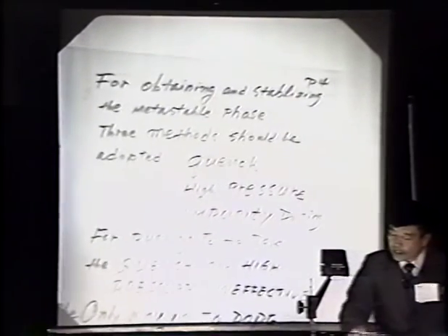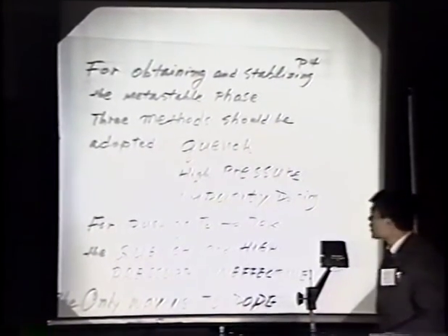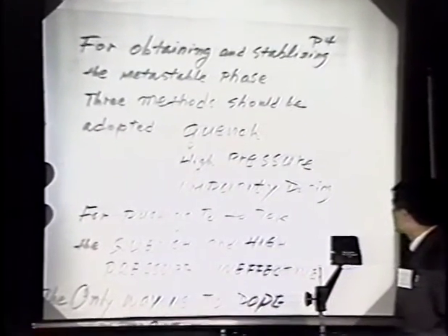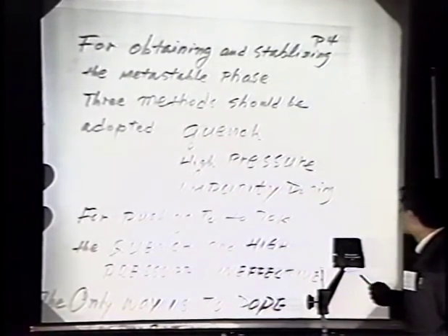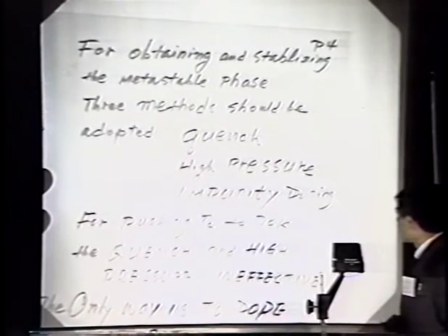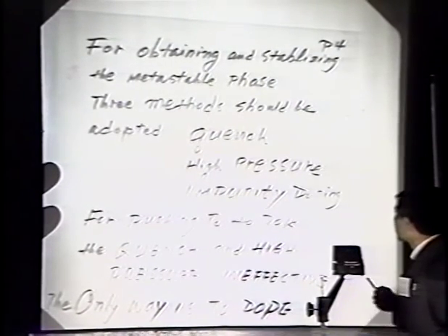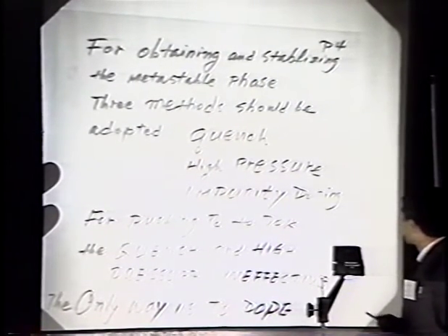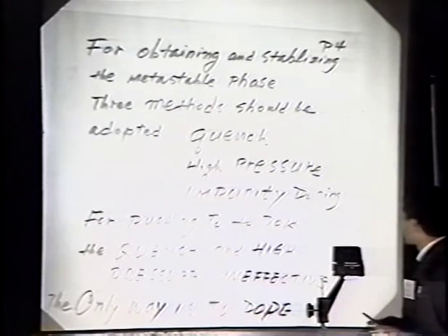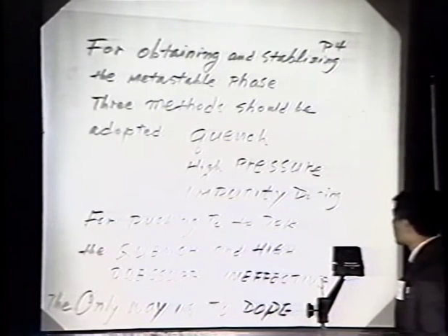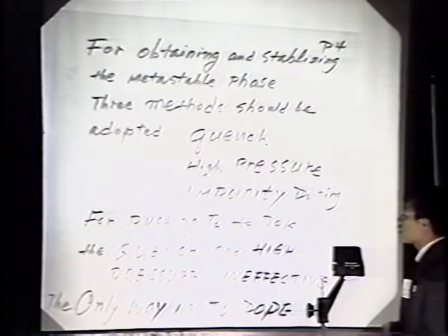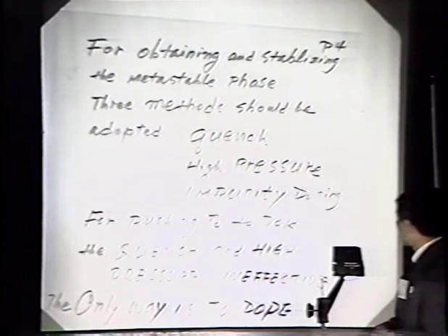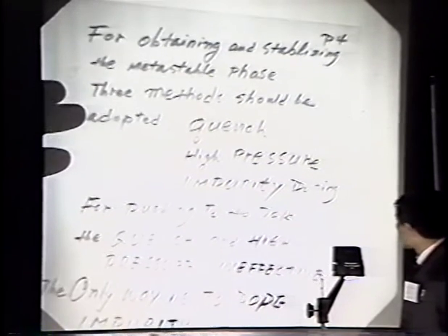For obtaining and stabilizing the metastable phase, three methods should be adopted. One is quench, second, high pressure, and third, impurity doping. For pushing the TC to 70K, quench and high pressure were ineffective. I did some experiments using quench and high pressure, but we haven't got a sample with the high TC. The only way left is doping impurity.